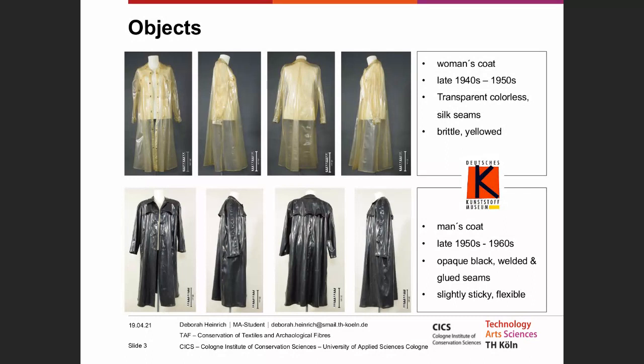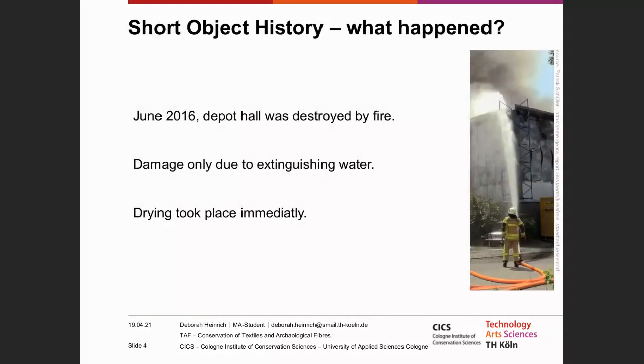However, both objects share a part of the history through which they came to me. Both objects were located in the same depot hall at Messe Düsseldorf, which was destroyed in a fire in June 2016. The part of the hall that housed the objects was well protected from fire, so that most of the damage was not caused by fire, but by moisture ingress from water and soot. Since the objects were inspected and dried immediately, further damage was prevented. Nevertheless, there are residues of the water, such as lime and dirt, on the objects.